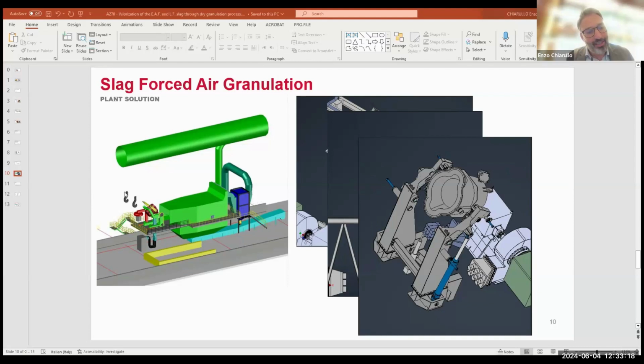We have a big granulation chamber in order to avoid that anybody can be injured by the flows of slag and air. We have the connection to the existing fume treatment plant. The air used for the granulation has to be treated in the main dedusting system. Here on the right, you can see the tilting mechanism we developed for this kind of technology, together with the nozzle of the fan, for performing the blowing of the system.